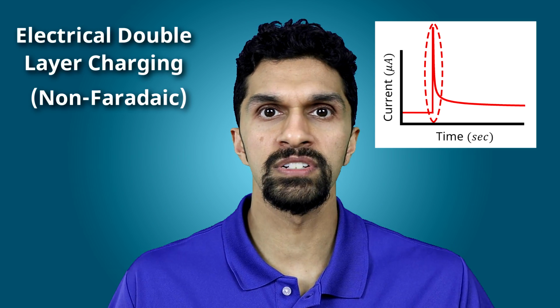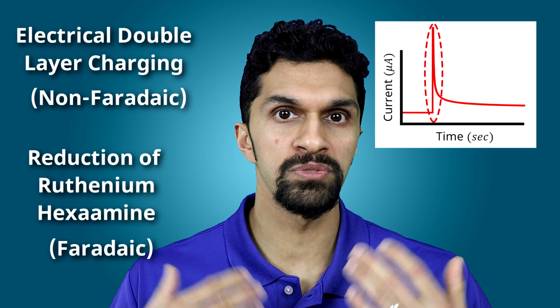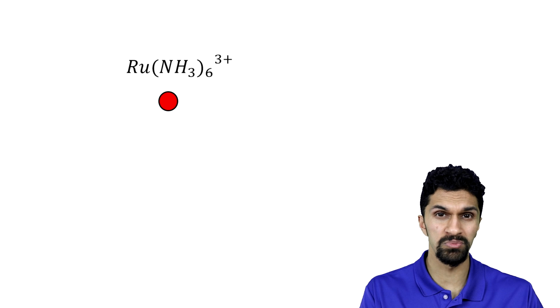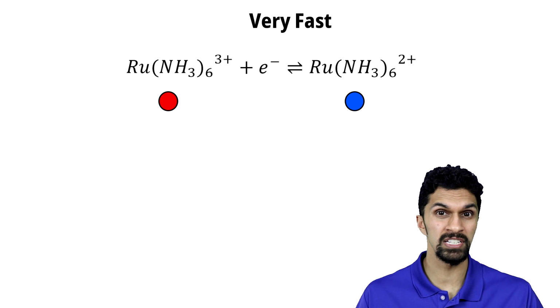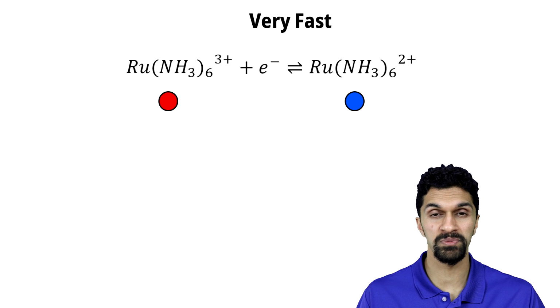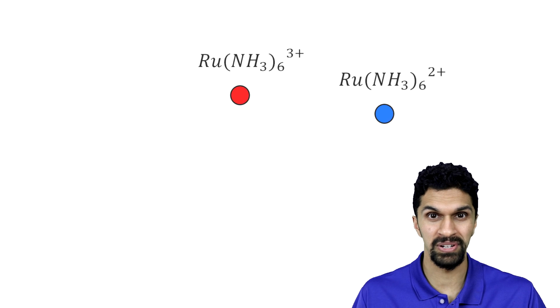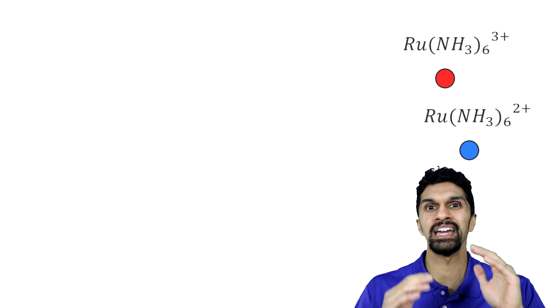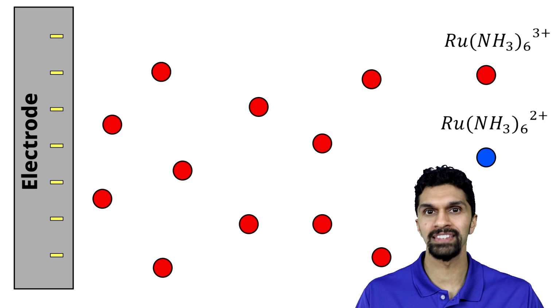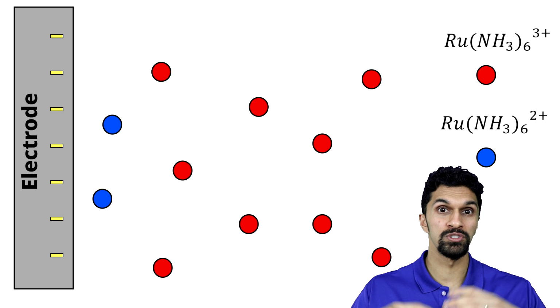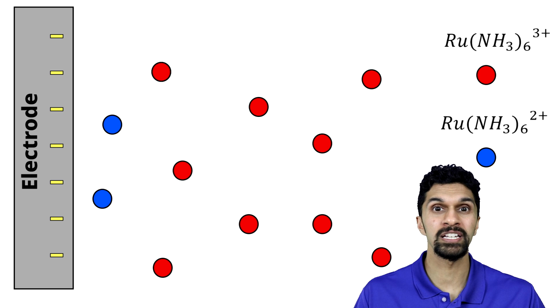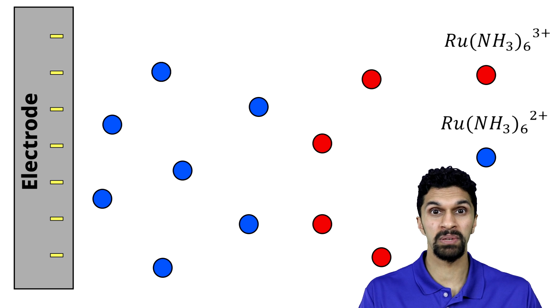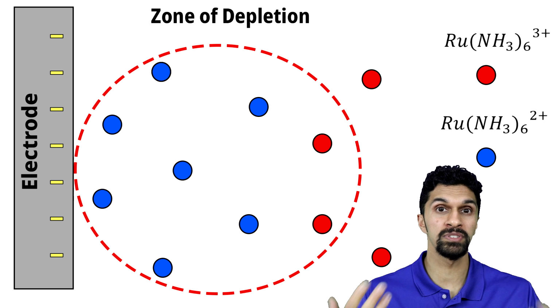The other factor is the Faradaic current associated with ruthenium hexamine. The reduction of ruthenium hexamine from the 3+ to the 2+ oxidation state is one of the fastest electron transfer processes in all of electrochemistry. This results in a concentration gradient at the electrode surface, where we start to lose, we deplete ruthenium hexamine 3+ near the electrode surface, and we have a lot more ruthenium hexamine 2+. This is sometimes referred to as the zone of depletion.